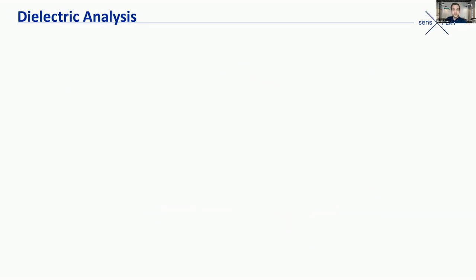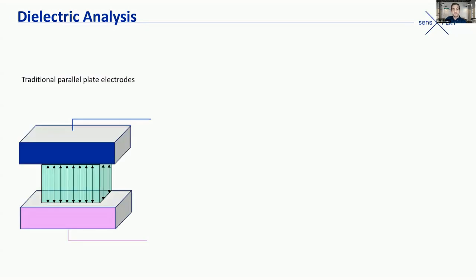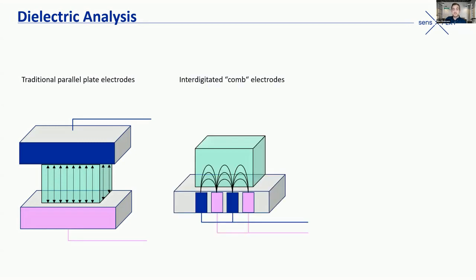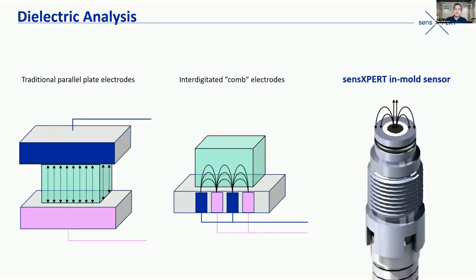Anyone who's familiar with dielectric analysis, even back in the 80s, you probably had something like this, where you had parallel plate electrodes, which is basically just a capacitor with the material in between. We've since been able to transition into an interdigitated comb electrode. So same type of configuration, but like little fingers that are kind of woven together. And that creates this fringe field and a flat single sensor, which is really nice for in-mold measurements. And this is actually what the sensXPERT in-mold sensor looks like. So that, again, is being installed in the mold, measuring the material behavior.